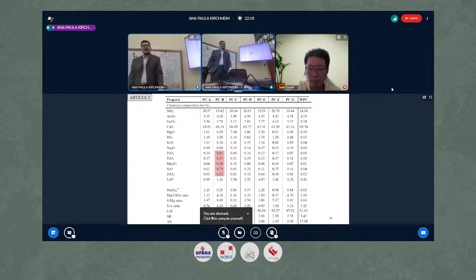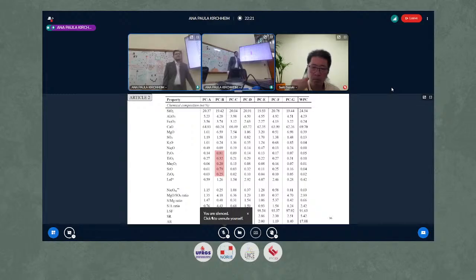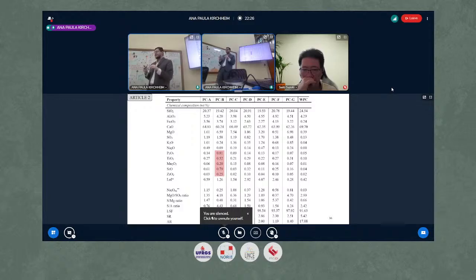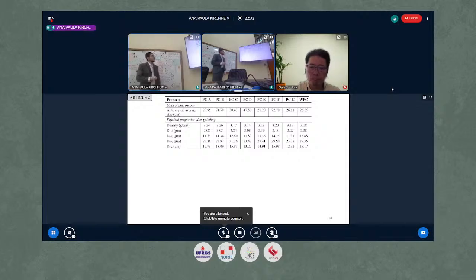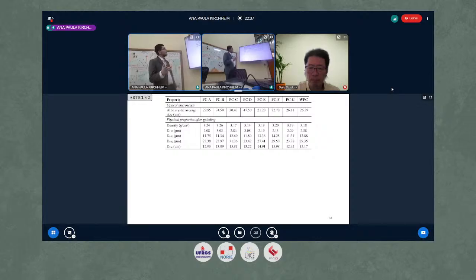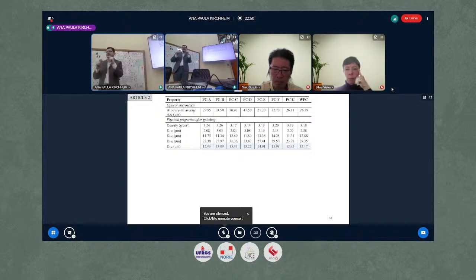And finally, I highlight that the PCB clinker has a high amount of minor elements, because this plant uses a limestone with low purity and a lot of coal processing. Here I highlight also the great variation in alite crystal size, from 21 to 74 micrometers. And here we use a different strategy from the first study: we vary the time of grinding to obtain different particle size distributions.